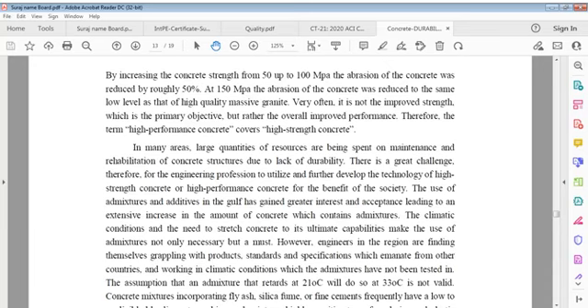By increasing concrete strength from 50 to 100 MPa, abrasion of concrete was reduced by roughly 50%. At 150 MPa, abrasion of concrete was reduced to the same low level as that of high quality massive granite.